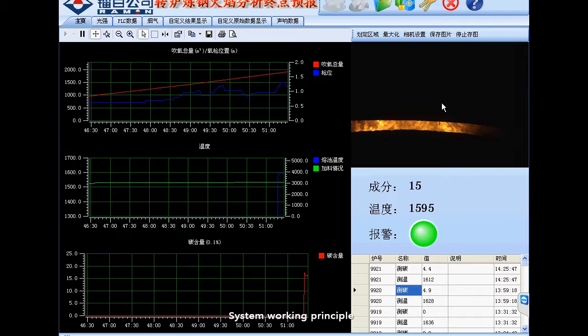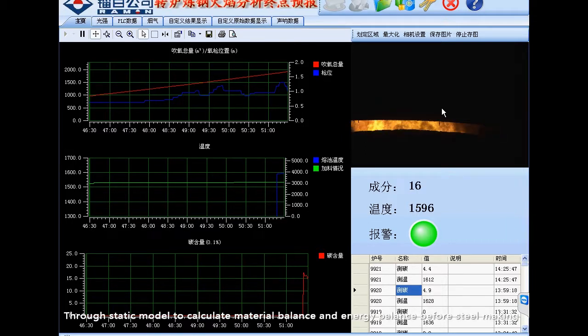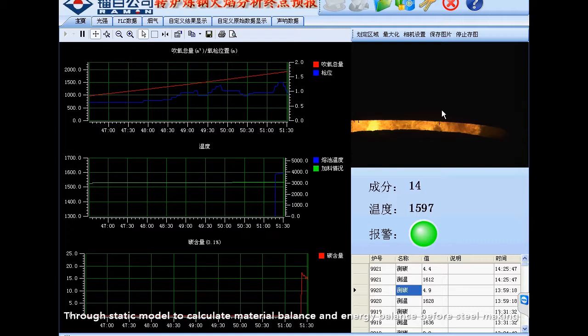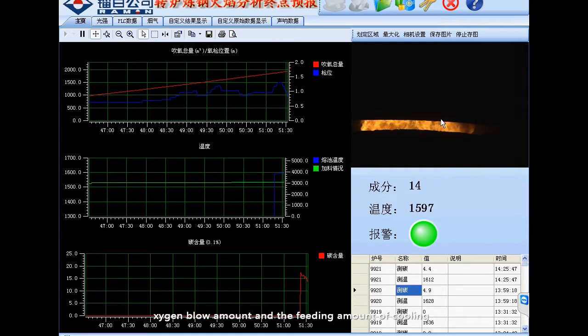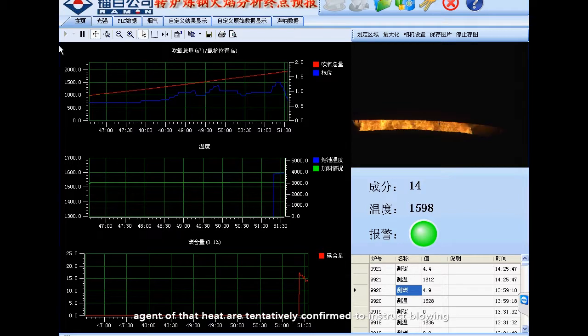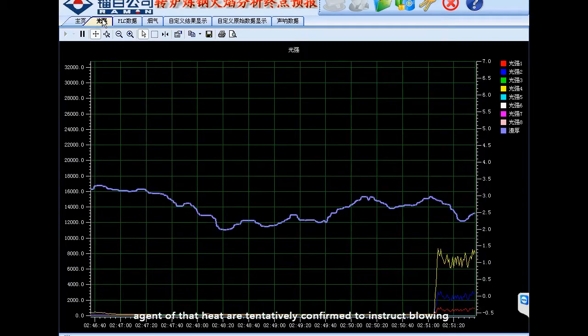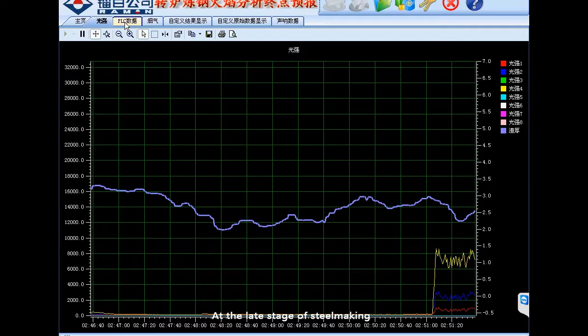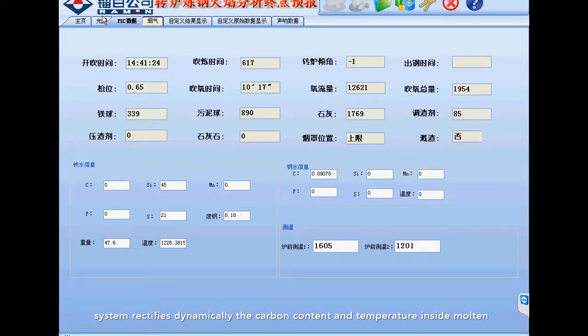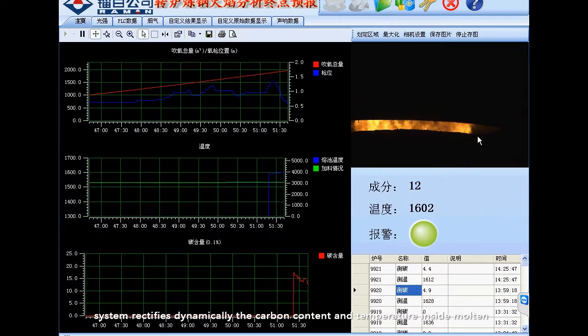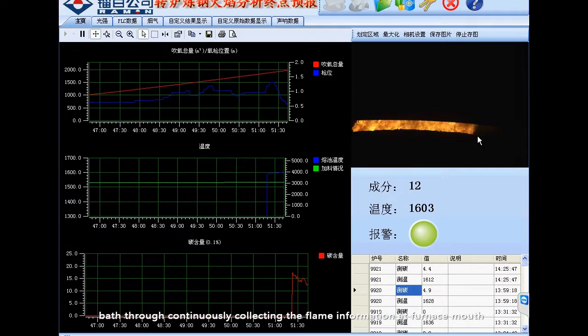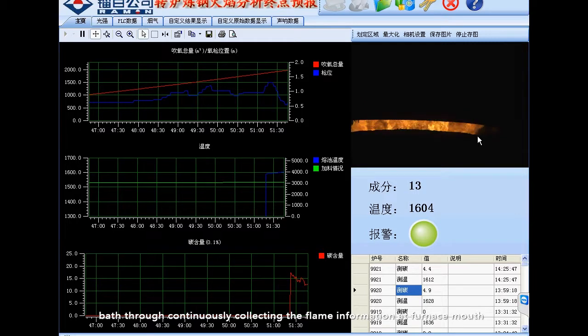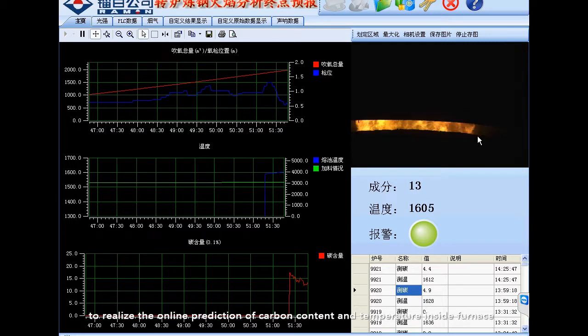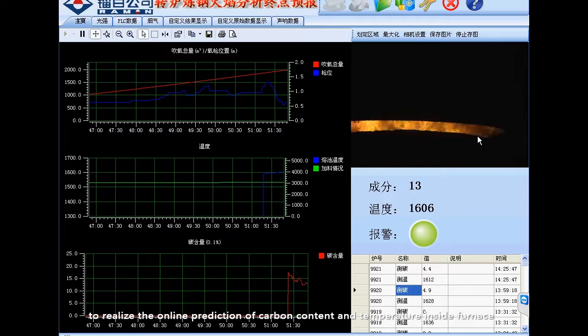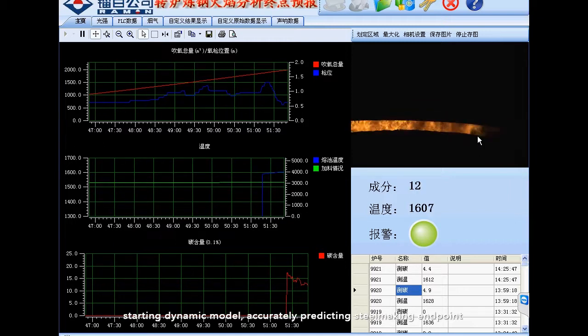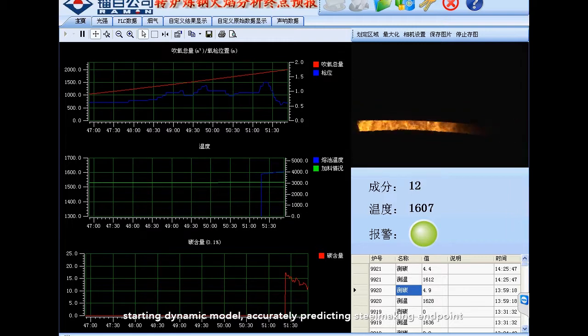System working principle: through static model to calculate material balance and energy balance before steelmaking, oxygen blow amount and the feeding amount of cooling agent of that heat are tentatively confirmed to instruct blowing. At the late stage of steelmaking, the system rectifies dynamically the carbon content and temperature inside molten bath through continuously collecting the flame information at furnace mouth to realize the online prediction of carbon content and temperature inside the furnace. Starting dynamic model, accurately predicting steelmaking endpoint.